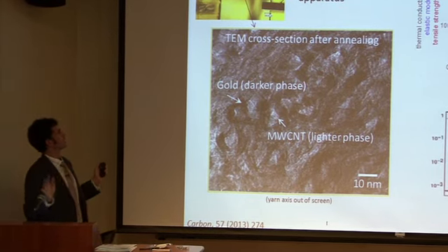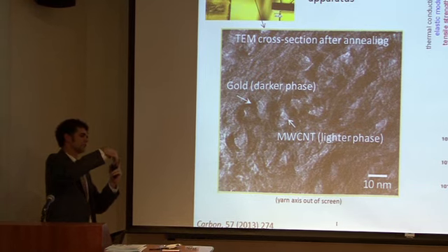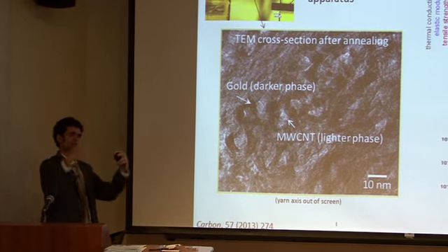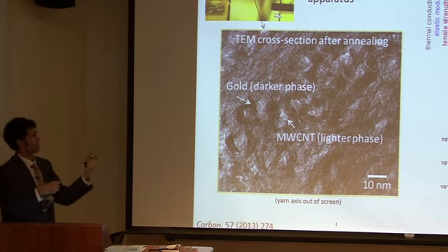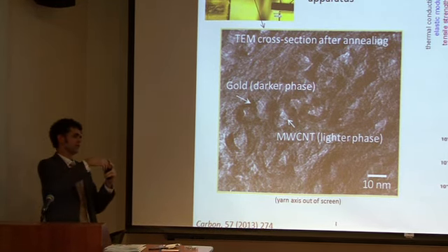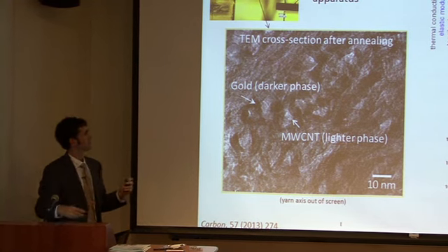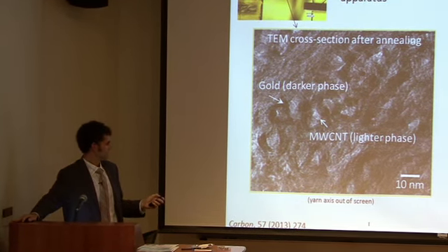We didn't think we were going to be able to spin them at all because, as I described to you, they rely on those weak van der Waals forces between nanotubes to pull each other off of that substrate and maintain continuity as they're spun into yarn. We thought the metal would interrupt those forces and make it weak, maybe even too weak to spin. But that wasn't the case at all. We actually had this increase. And there's a reason for that.